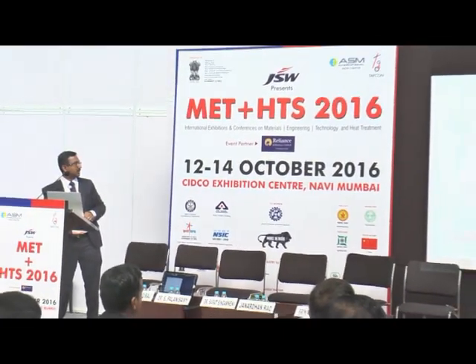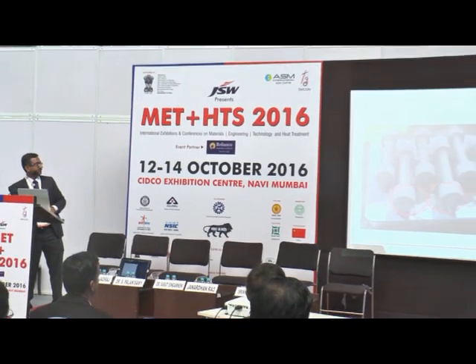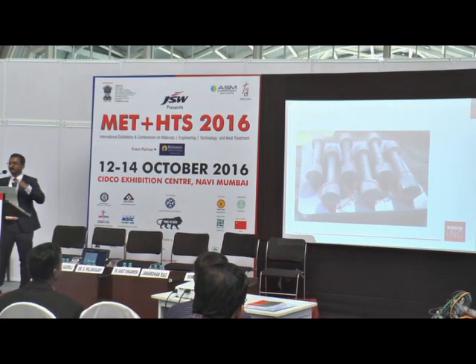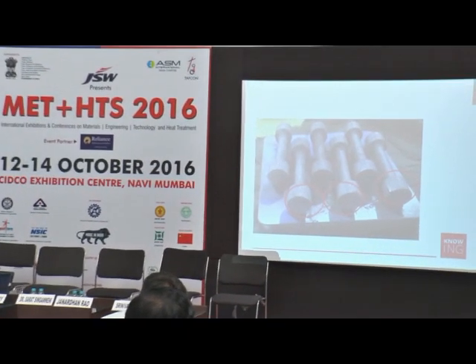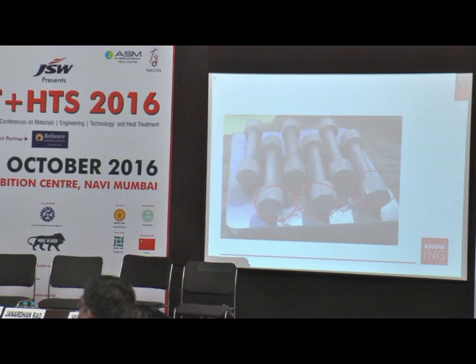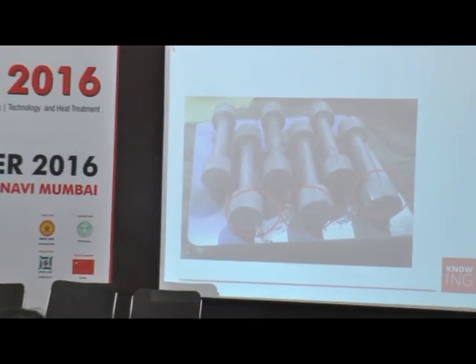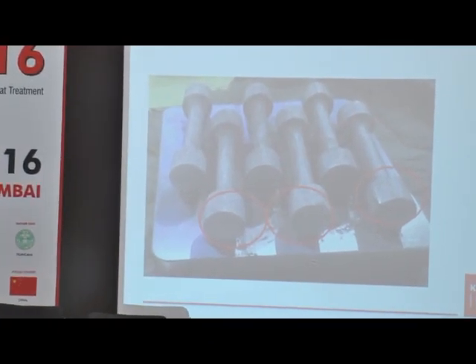Just to show you an example of what we faced when we recycled the powder. In this particular case, you can see the tensile samples we prepared. It opened up, because again the powder particle size was different. You can see it there, here, and also here. The surface couldn't close properly, because even though we started building it, we didn't stop building it. We should have stopped it there, but we kept building the part. And when the stage goes down and the powder particle size is not uniform, obviously you have issues like this.